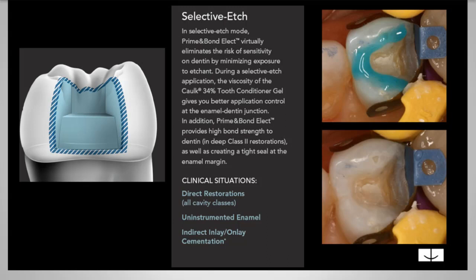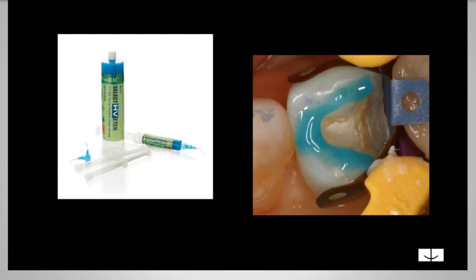So here's a product that if you're using select etch, I would definitely recommend. It's select high viscosity etch by Bisco with benzalkonium chloride in it. So here you can put it on. It's sometimes a little bit harder to extrude, but it doesn't move. And so you're able to just etch the enamel. And that's something I really like if you're using select etch. So if you're doing a select etch portion, that's what I would use.